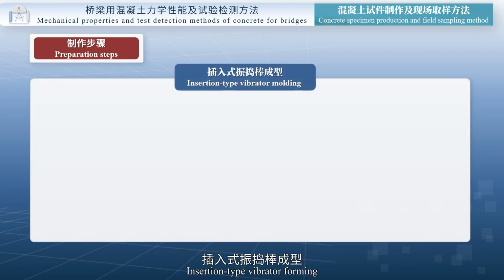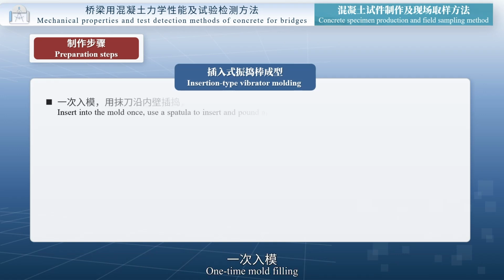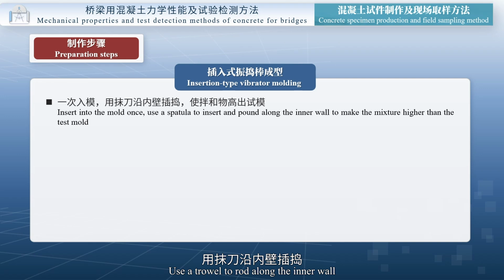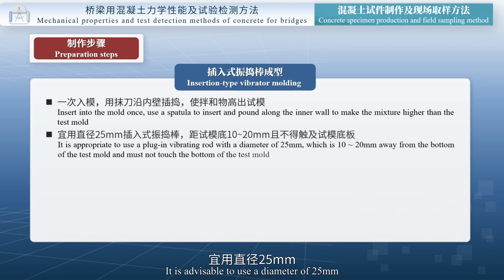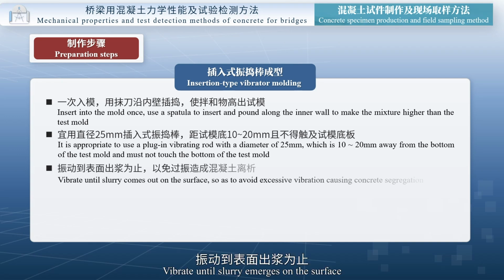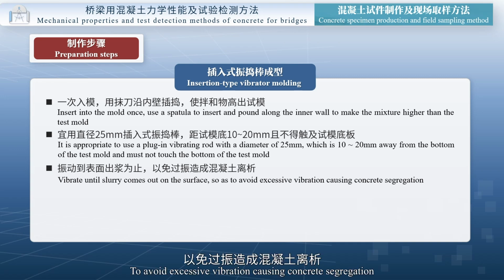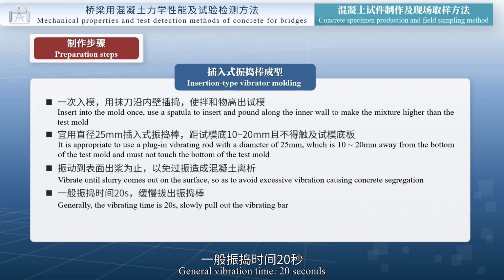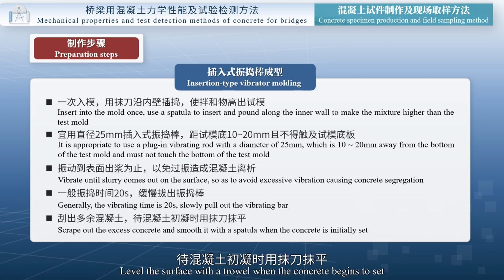Step 4. Insertion type vibrator forming. Fill the mold in one go. Use a spatula to insert and pound along the inner wall, making the mixture higher than the test mold. It is advisable to use a vibrating rod with a diameter of 25 mm. Insert the vibrating rod 10-20 mm from the mold bottom, and it must not touch the test mold base plate. Vibrate until slurry emerges on the surface, to avoid excessive vibration causing concrete segregation. General vibration time is 20 seconds. Slowly withdraw the vibrating rod. Scrape off excess concrete. Level the surface with a trowel when the concrete begins to set.